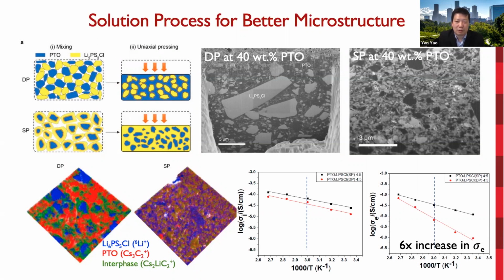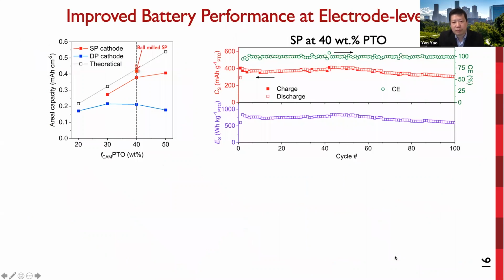We note here, typically reactions between cathode and electrolyte are to be avoided or suppressed. For example, on NMC particles, an oxide coating is used. However, here is an example showing the reaction between cathode and electrolyte can be used for the benefit of forming a better microstructure. So as a result, the area capacity now scales with PTO mass fraction in this red line. In comparison, the dry process is the blue line. So the material utilization actually can go up to 98%, and cycling stability is excellent over 100 cycles.